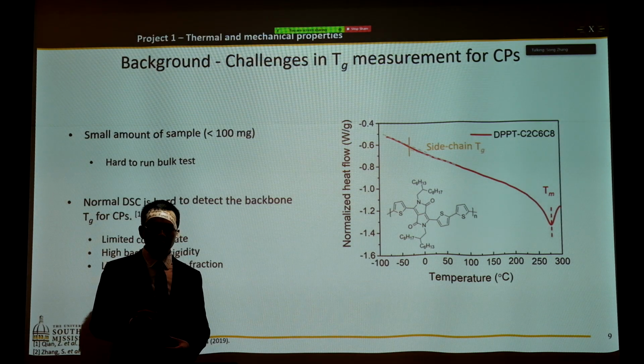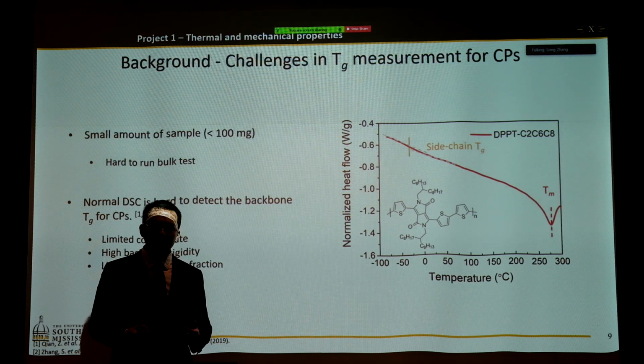And why is that? The first reason is that DSC only provides us a very limited range of cooling rates. Secondly, due to the rigidity of the polymer backbone, the step change of heat capacity upon heating is very limited. So DSC does not have the sensitivity to detect that step change. And also, since they are semi-crystalline polymers, the amorphous content is very limited.